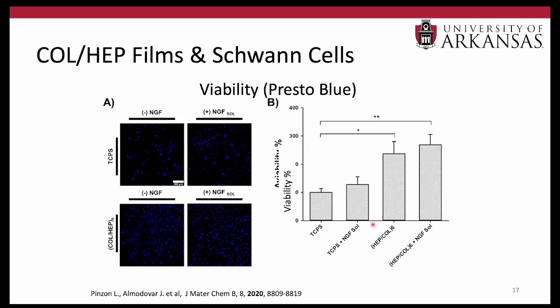All right, then we went ahead and investigated the behavior of Schwann cells on these surfaces, and we initially performed a viability study where we culture the cells on our control surfaces, polystyrene with or without NGF, or on our coatings with and without NGF. Interestingly, we saw that there wasn't a huge difference between the conditions with and without NGF in either surface. That's okay. But we see a very drastic difference in viability in the conditions where we have our heparin collagen coatings, compared to the uncoated polystyrene control.